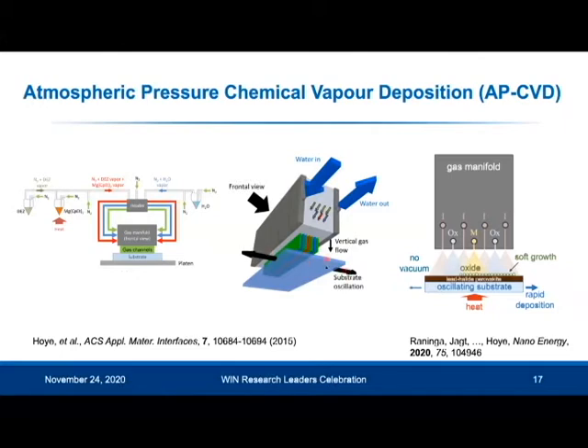Now, if you have a very small spacing between the bottom of the manifold and the top of the substrate, then you can ensure that each of these different gas channels is spatially separated from each other. And here you have the metal precursor gas channel. These blue channels are the oxidant channels, and these are separated with these inert gas channels. So if you ensure there's spatial separation, then you can achieve ALD much faster and in open air. So you have heard about this from Professor Musselman.